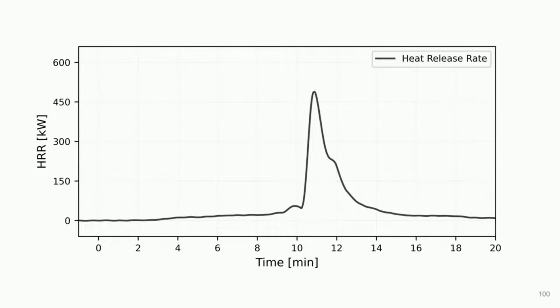This graph shows the heat release rate, HRR, that we measured from the beginning of experiment 21, starting at time 0, essentially on the left, to the end of the experiment after 20 minutes. And we ran all of these experiments for 20 minutes, unless, of course, they ended much sooner than that, or unless we had to stop for health and safety reasons. The HRR on the vertical axis is effectively telling us the size of the fire in terms of the amount of energy it's releasing at any given moment in time. So the higher that line, the more energetic the fire is.